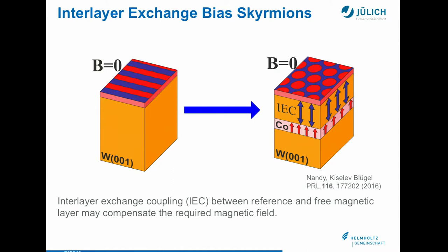And the question is now, how do we tune the thickness of the cobalt layer and the number of tungsten layers such that we are in the right ballpark? This we have done, but by observing that if the cobalt layer becomes thicker, the magnetization becomes in-plane. This is very bad. We need out-of-plane magnetization. And therefore, we have to slide in another platinum layer of certain thickness, so as to stabilize the magnetization to be out-of-plane.